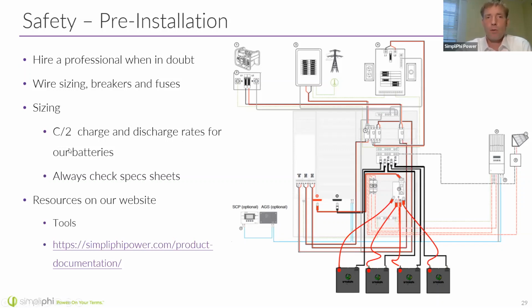If you follow our C/2 discharge rates, you can expect many years of success from lithium iron phosphate batteries. In fact, if you really take good care of your batteries, you could expect 10,000 cycles out of them. If you do cycle once a day, that would be 27 years, right? Lithium batteries, especially lithium iron phosphate batteries, greatly exceed the performance of lead acid batteries, which is why this industry is so exciting. We have a lot of resources on our website. I'm going to point those out to you.